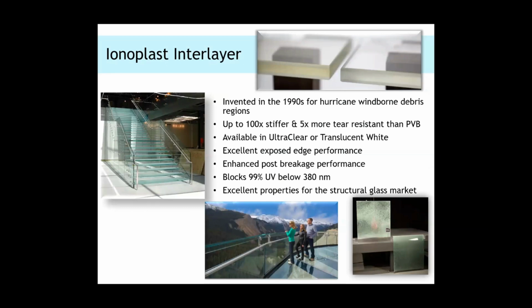Ionoplast was invented in the 1990s, specifically for the hurricane windborne debris regions. At the time, PVB was not strong enough to stay in the frame during some of the high pressure cycling testing. Ionoplast is 100 times stiffer and 5 times more tear resistant than PVB. It's available in ultra clear and translucent white. One advantage is if the glass has exposed edges to the environment, the ionoplast weathers very well. We have 25 years of weathering data now in Hialeah, Florida, where the edges look great.